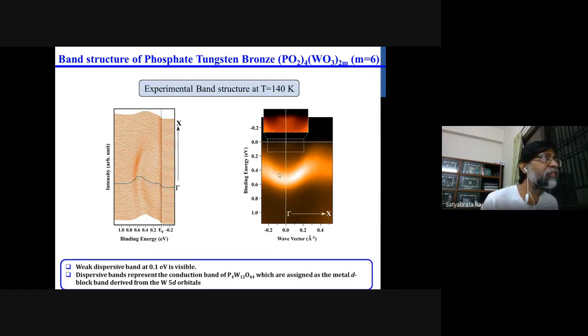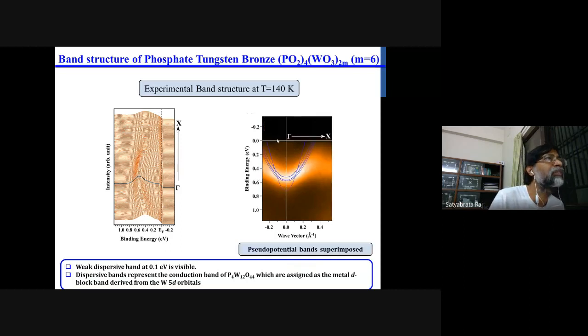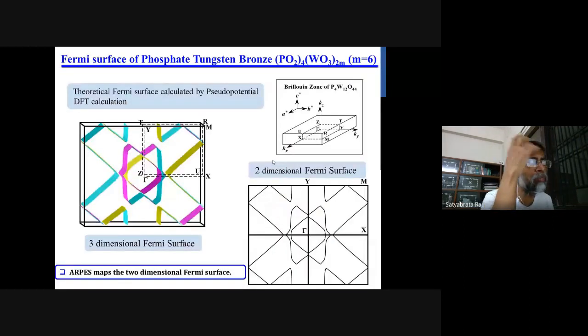So this gives the valence band spectra above this anomaly temperature. We have measured and overlapped them with the calculations. These are not important. We have also calculated the Fermi surface, and you can see the Fermi surface is very straight, with no dispersion along the gamma-z direction. That is because of the two-dimensional nature, and that's why we have overlapped.